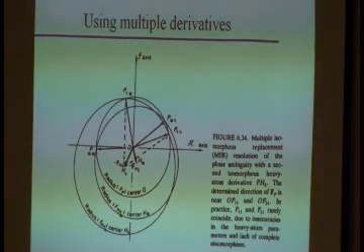Okay? There's actually one point where 2 circles intersect, one other point where 2 circles intersect, and then there is an area where the 2 intersection points are very close to each other. This was done from real life data, okay? That's why you don't get one exact intersection point for the 3 circles. There's error in your data.